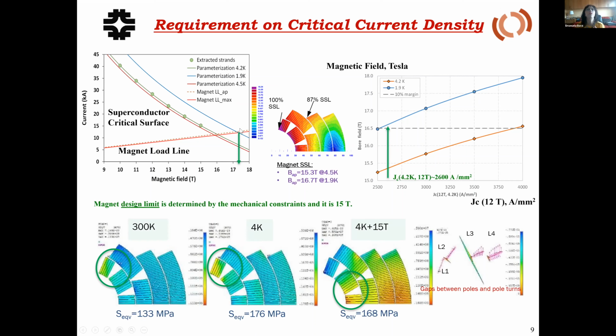So for instance, if they want to achieve, at 4.5 Kelvin, let's say, 16 Tesla, they need a superconductor whose critical surface... these are the critical surfaces of the superconductor niobium-3 tin at 4.5 and 1.9 Kelvin. So the point of intersection between your load line and the critical surface of your superconductor determines, in principle, the potential performance of your magnet. So here you can see we are in the region above 15 Tesla.